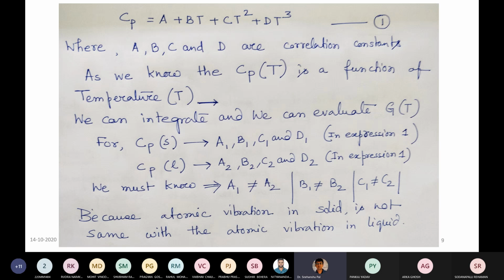Now, consider a scenario where Cp equals an expression A plus Bt plus Ct square plus Dt cube, where A, B, C, and D are the correlation constants. Now we know that Cp is a function of temperature. If we integrate Cp by T dt, we get the entropy. If we integrate Cp dt, we get the enthalpy. And in the process, we can evaluate G of T. We are talking about liquid and solid.